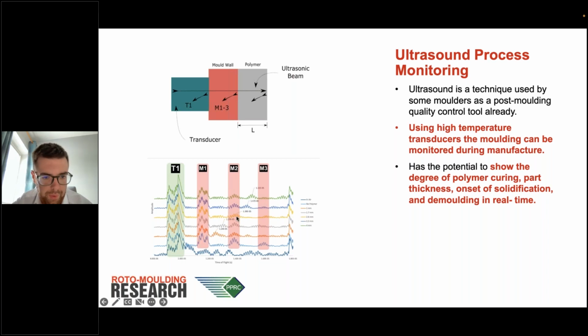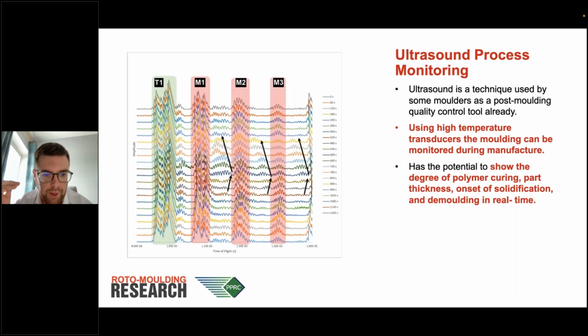So the initial indications were that you could indeed see the polymer on the back face of the mold, and not only that, you could pick up the thickness of the polymer sheet that's placed on the back face of the mold. So I took that a step further, and I did a 1 kilo molding on a tank mold, which is the one that you saw in the picture previously.